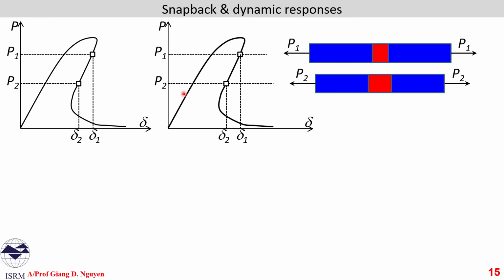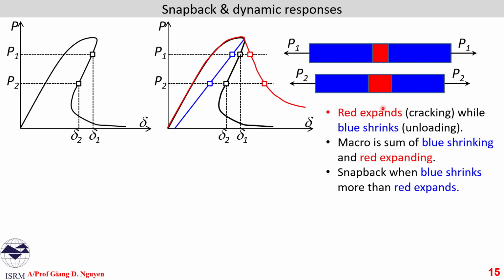So if this is the macro load displacement behavior, it is the combination of two behaviors inside and outside the fracture process zone. The red zone here is expanding, while the blue zone is shrinking. They are under the same stress condition, or the same load, if the cross-section area in the red and the blue zones are the same, which is the case assumed here. So the macro one is the volume average of the red and blue ones. Snapback happens when the blue one is shrinking more than the expansion of the red one.